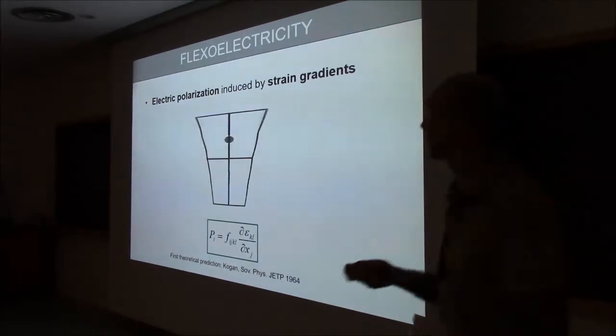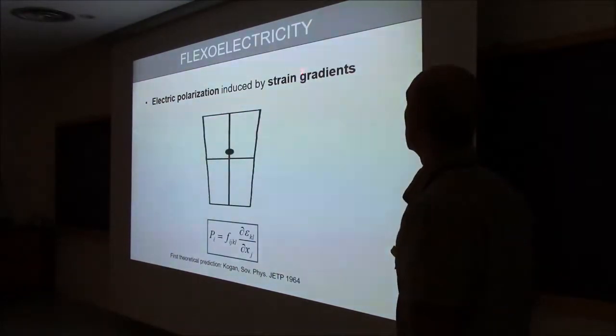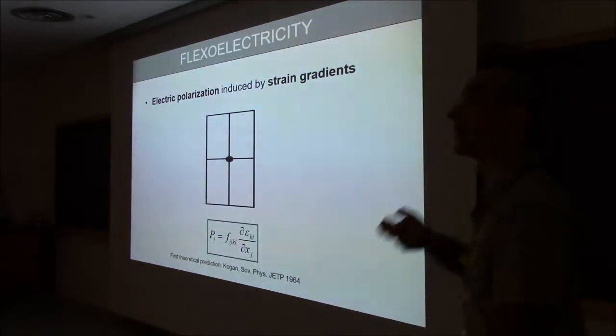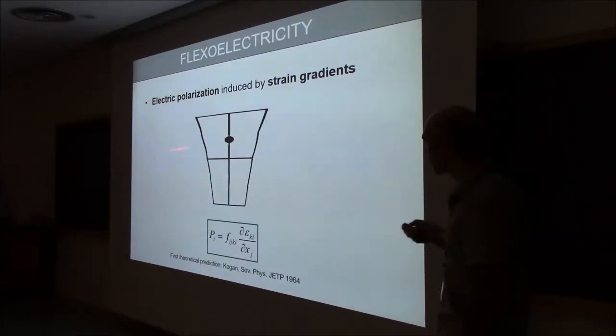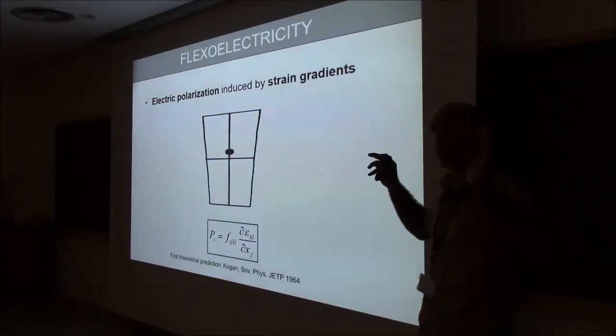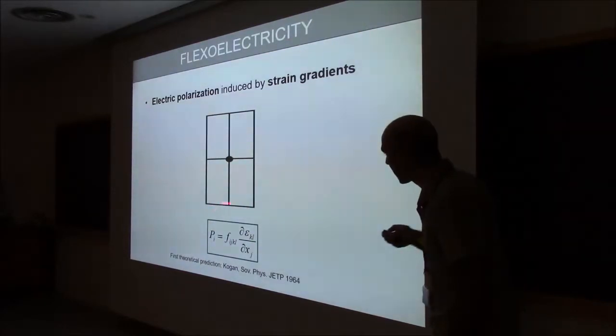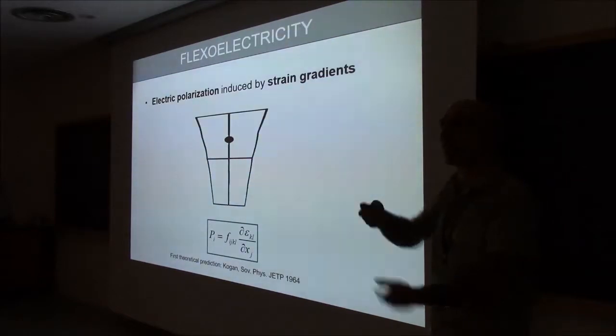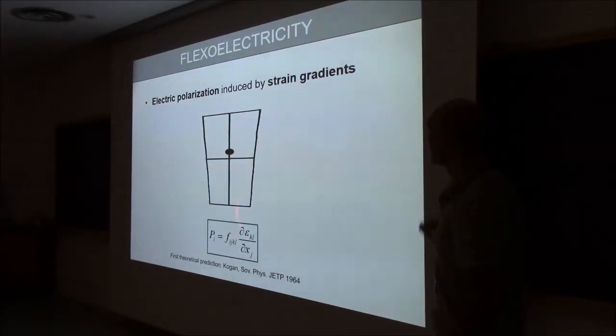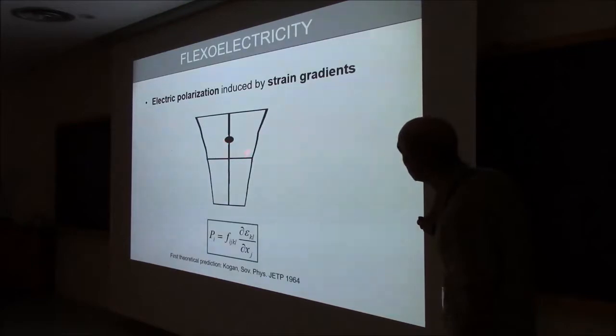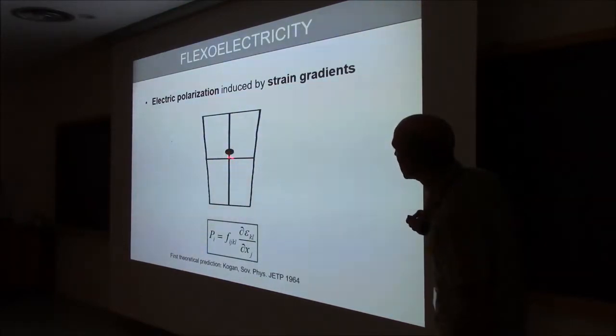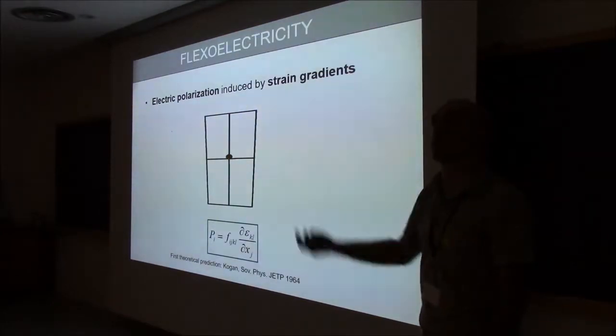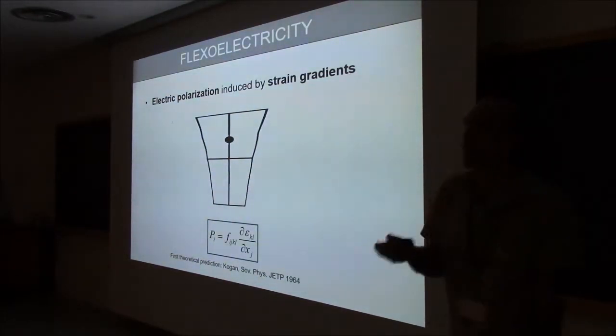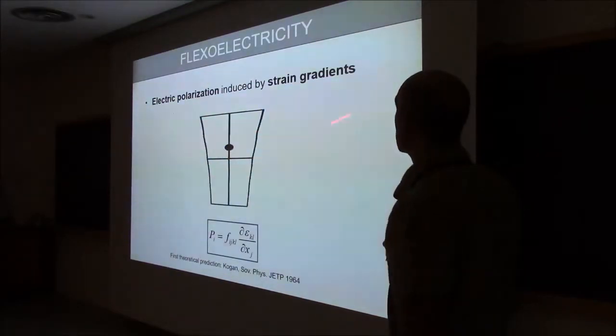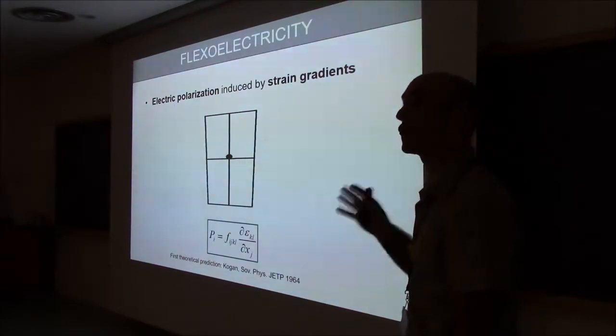So what is flexoelectricity? Flexoelectricity is a dielectric polarization induced by a strain gradient. Strain gradient is a difference in strain. And I always use this figure to illustrate it. You can start with a perfectly centrosymmetric unit cell. And if you apply some compression at the bottom and some extension at the top, now you have a strain difference, which divided by the size of the unit cell will be the strain gradient. And it may happen that when you do that, because there's now more space available at the top of the unit cell, this cation here may want to move up, thereby giving you some polarization. So that's a bit of a cartoon image of what happens, why it is possible to get polarization just from strain gradients, even in unit cells that are centrosymmetric to start with.